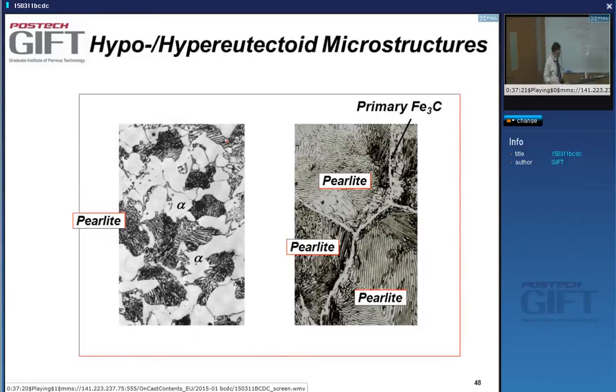All right. Now, many steels are basically iron-carbon alloys. Depending on the amount of carbon we have in the alloy, we'll get a different phase fraction of ferrite and cementite. The problem is when you look at the microstructural level, you don't see ferrite grains and cementite grains separately. What you see is ferrite and perlite. It means the cementite forms perlite together with a fraction of